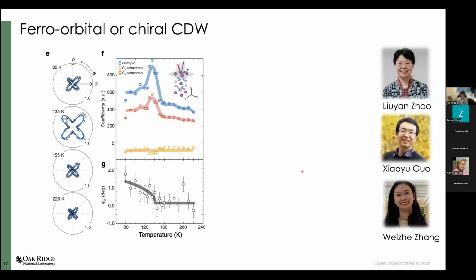And then we want to ask a little bit more, exactly what the point group is. Then we asked Liu Yan from Michigan to help us check the second harmonic generation. So here is the azimuthal dependence of the optical measurements, and here is a fitting of these patterns. Again, we can confirm that throughout the CDW transition, there's no C4 rotational symmetry breaking.